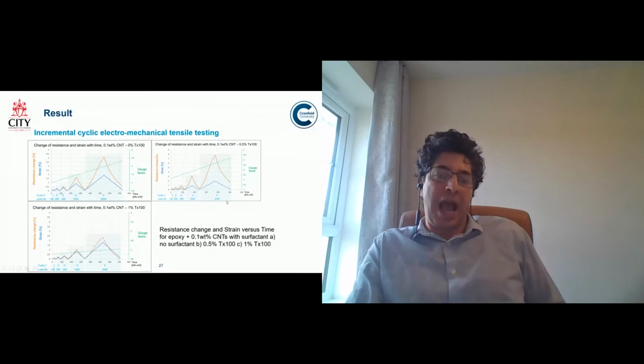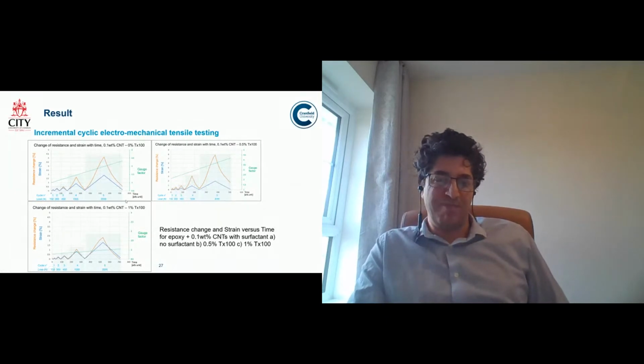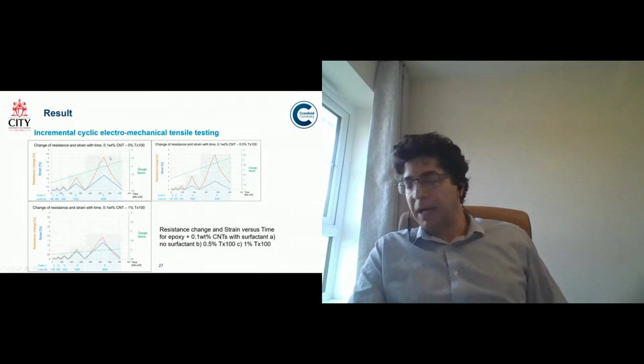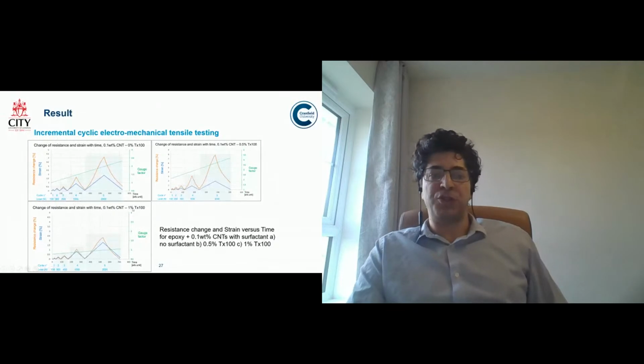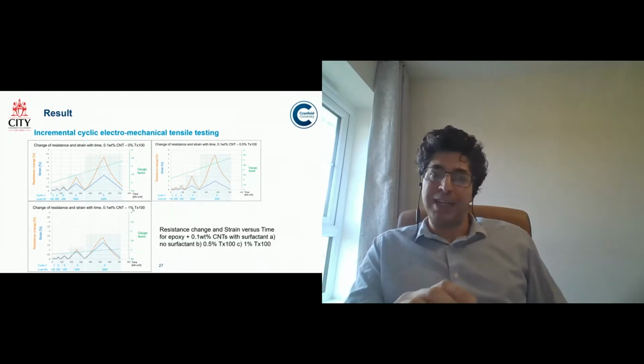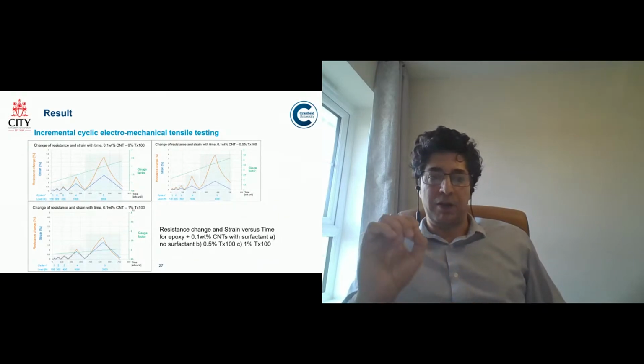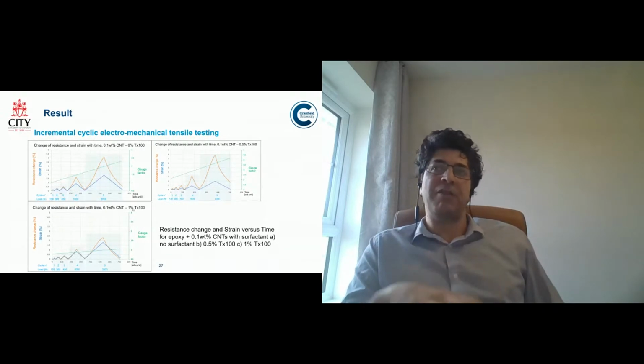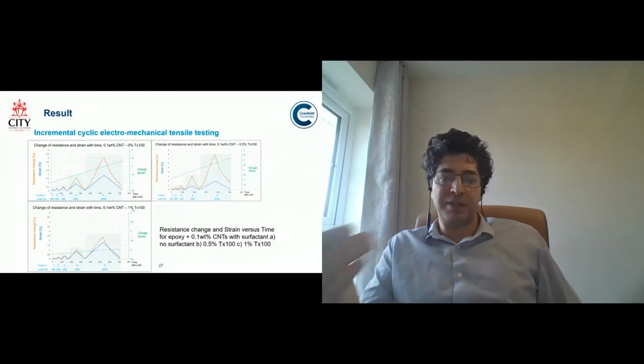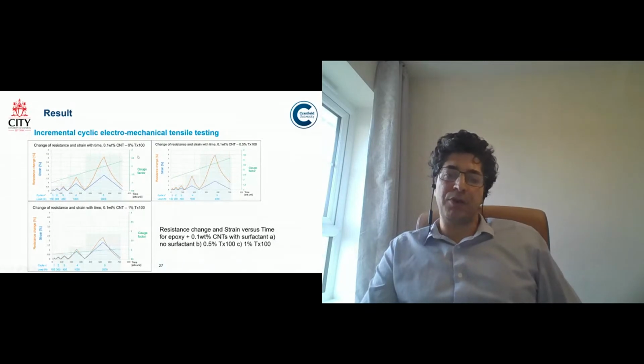And we ended up having some failures at the end, let's say the ultimate failure in this specimen, where we actually wanted not to have, or to be at the verge of the damage occurring inside our composite. But what I can say is that if you compare, for example, two curves of the orange one and the blue one, the one that has the highest difference is the best one, all right? Because at a very small variation of strains, we want a very high sensitivity of our smartness, meaning that we want the resistivity to be highly increasing or decreasing with a very small or tiny amount of strain variation. That's what makes a very good sensor a very good sensor, and that's been identified with the gauge factor. So you can guess that, for example, the top right image would be the most desirable image of this difference, because that has the highest resistivity change with the blue line, which is cyclic load.